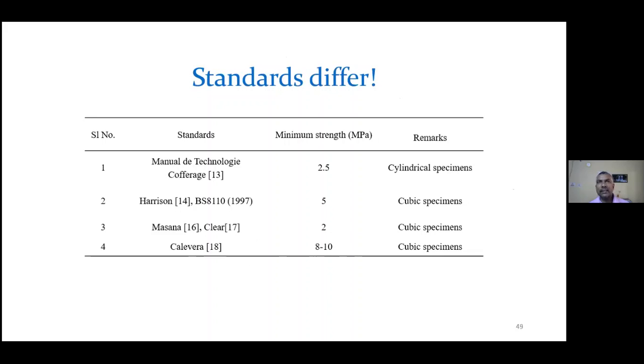If a column concrete can stay alone without the support of the vertical formwork, then we can remove the vertical formwork. And this is the concrete strength that codes and literature suggest is required for removal of vertical formwork. Here also you can see it varies from 2 megapascal to 10 megapascal in different literature. So much variation. So which one to trust?